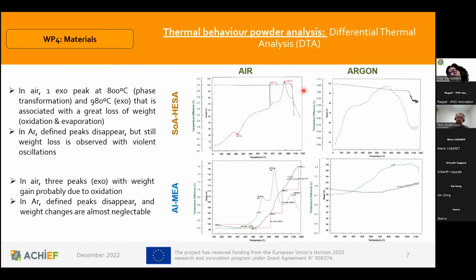When we perform this analysis in argon, the situation changes and this material behaves better, but in that case, with the state-of-the-art HEA, almost all these peaks disappear, but we still have some weight loss because of some kind of evaporation.